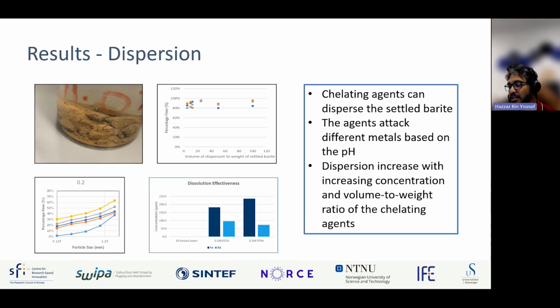So our next job was to find a solution. The solution is to break this sag barite. If we can break it, then we can circulate, and if we can circulate, we can free the formation and pull the casing out. So we have to find a way to break this sag barite. There are two ways. One is if we can take the iron out. If we can take the iron out, we are destroying the bridges between the particles, which weakens the particles and solves the problem. Or we can go to the barite itself. If we can dissolve a lot of barite, that helps us to weaken this sag barite formation.